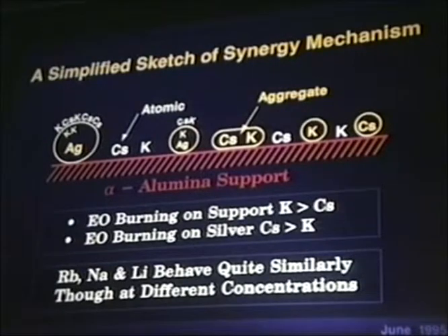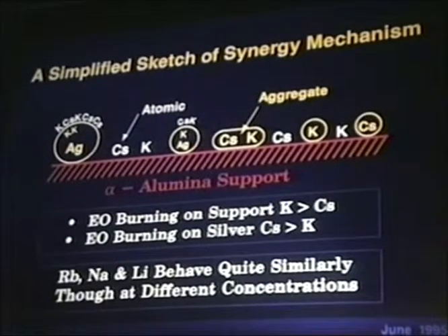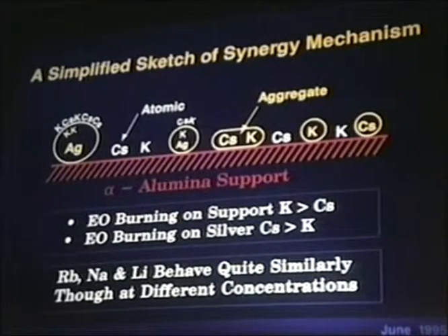Cesium and potassium are present in aggregates which can range from atomic to several tens to hundreds of angstroms. Thus, the mixture of potassium and cesium has the advantage of both these inhibitor and promoter types of action. This is quite consistent with the work of Professor Lambert, where he has shown that the bulky cesium sits on top of silver atoms in single crystal studies, while the potassium, a smaller cation, can indeed go subsurface. This leaves surface sites available on a potassium-promoted catalyst more so than on a cesium-promoted silver catalyst.